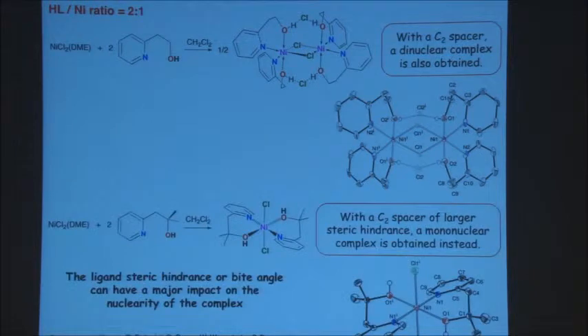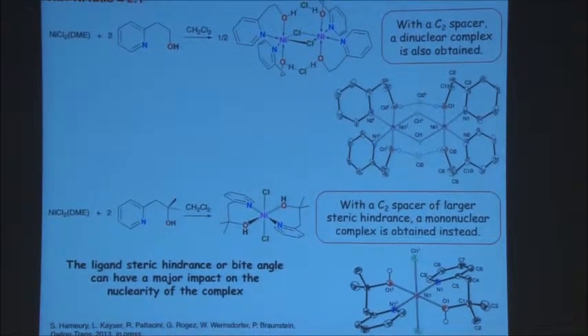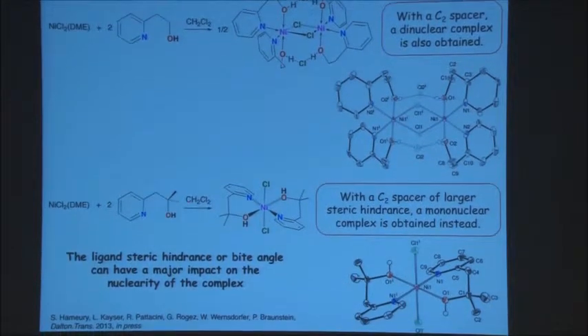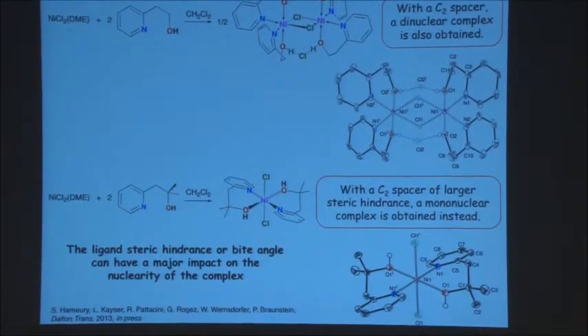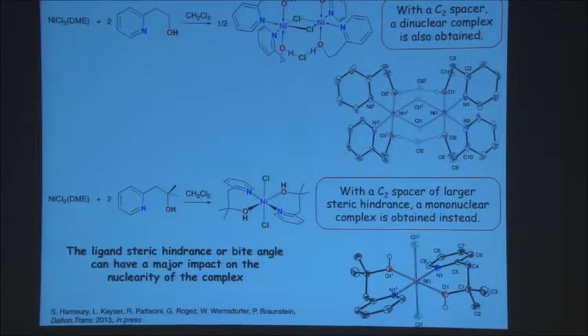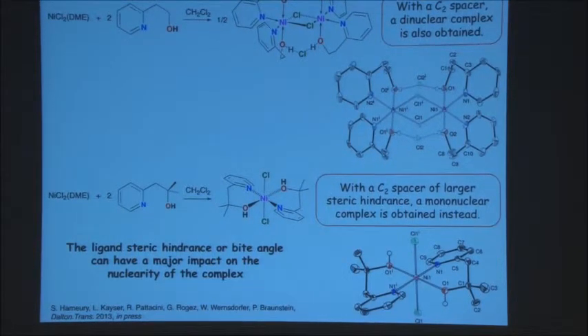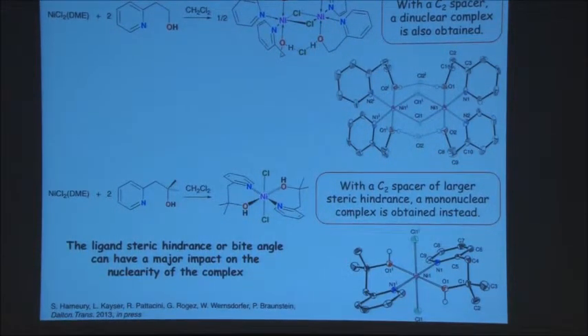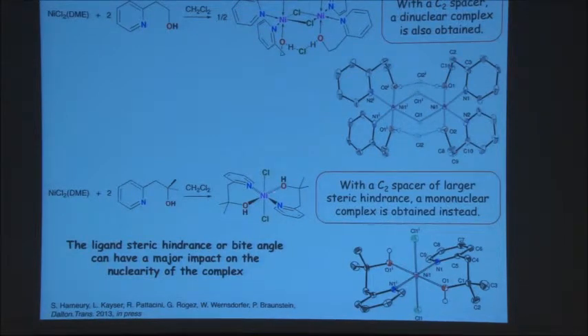Now, if you look at these systems here and compare with the dimethyl substituted spacer with the gem-dimethyl group, now you see a totally different structural type appear. Now we have a mononuclear compound, still with a 2-to-1 ratio in terms of ligand to metal, bischelating here. But we have a nickel center which is octahedrally coordinated with the two chlorides bound to the nickel center. And this is established by X-ray diffraction.